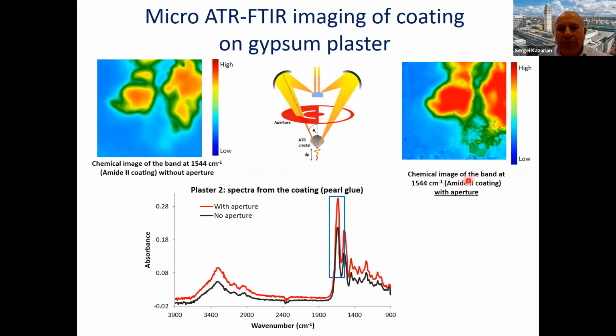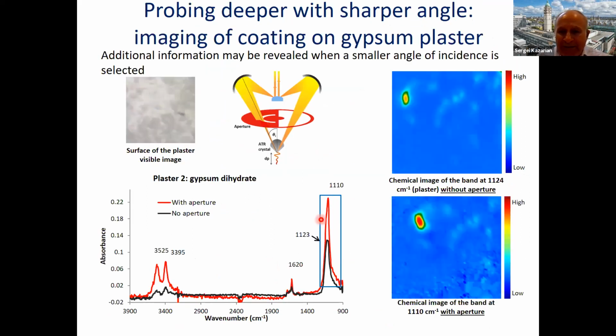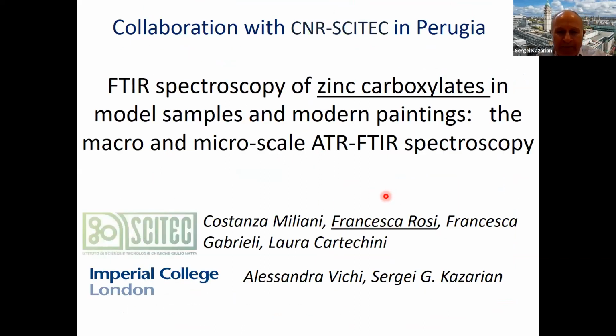And here, using different apertures, we were able to obtain different spectra and probe deeper. For example, it's particularly striking that these bands are much more visible when using a specific aperture to measure such types of samples. And Francesca Rosi already mentioned the painting by Jackson Pollock.